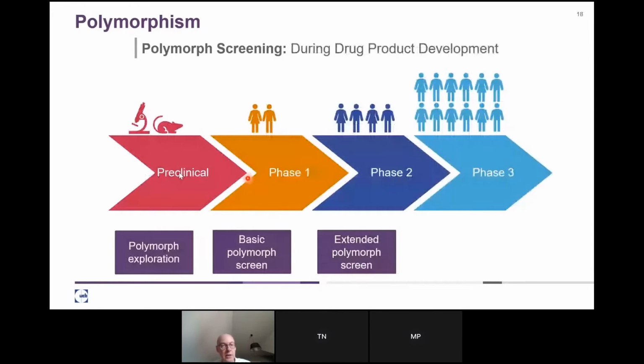And again, in view of the development phases, we typically do the polymorph screening about 3 times. We do it in preclinical before going to human. We do some exploration, mainly in solvents that you use in the process. During phase 1, when it survives phase 1, we do a basic polymorphic screen. And then when the drug proves its efficacy and you say, now we go for it, to make sure we did not miss anything, you go for an extended polymorph screen, which is really hundreds, or can be 400 or 500 experiments on milligram scale, to make sure that you did not miss a form. So that's the way we approach polymorphism.